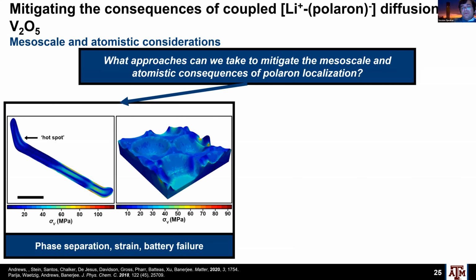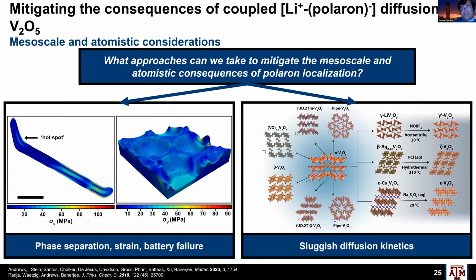polaron localization, right? So on the one hand, okay, so we've learned that phase heterogeneities, phase separation gives rise to accumulated stresses that then even at the macroscopic level will accumulate in all sorts of places and give rise to failure. And you can see this here at a bend in a pre-bent wire. We see hot spots that are being formed by scanning transmission X-ray microscopy, and then you can get sort of stress inhomogeneities. So I'm going to talk first about this left side, and then I'm going to come back here and spend a little bit of time thinking about really a chemical approach to electrode design.